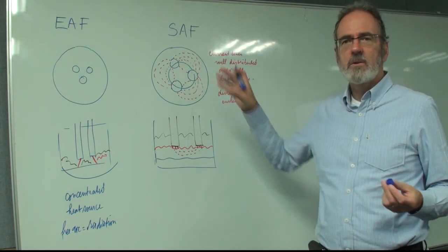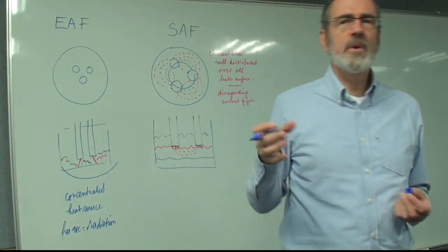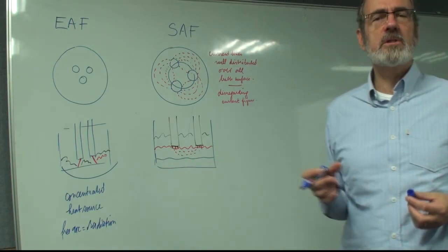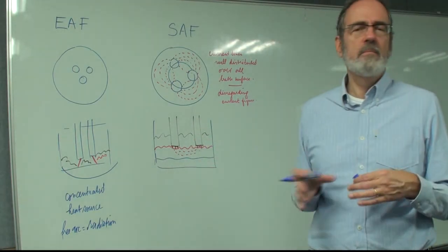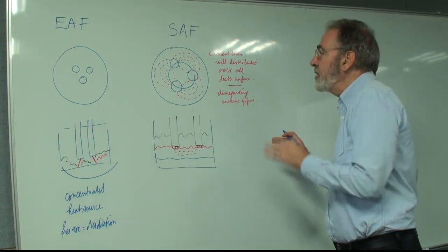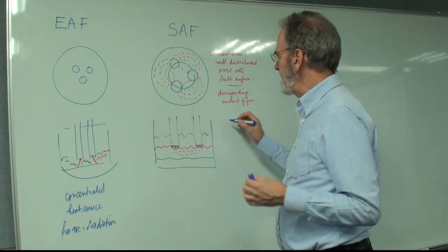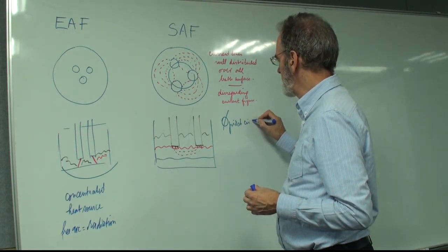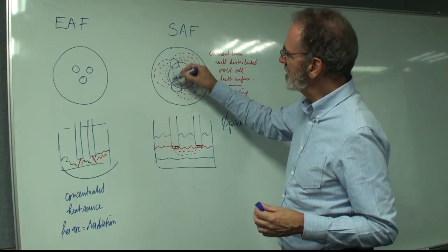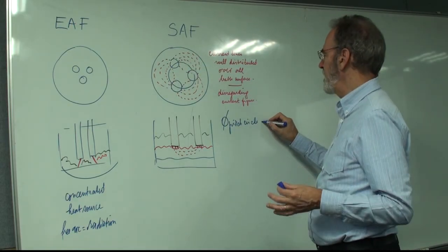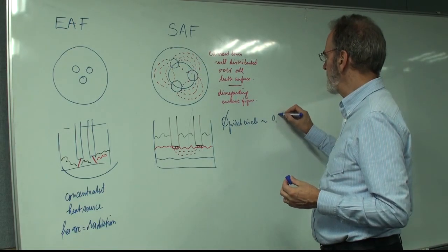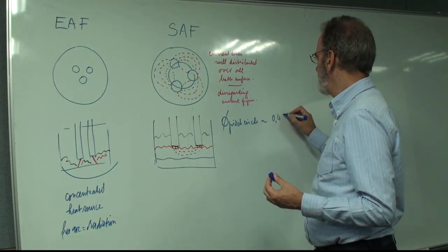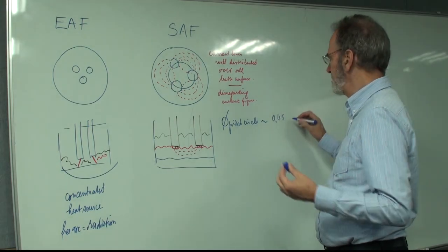So this you can calculate, assuming resistance of the slag. Many people have calculated this, and the result is that the pitch circle, meaning this circle, must be around between 0.4 and 0.5.